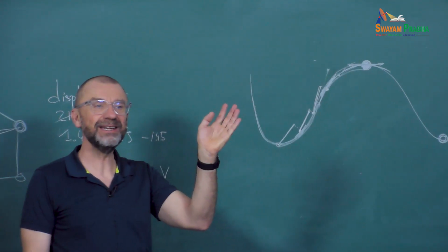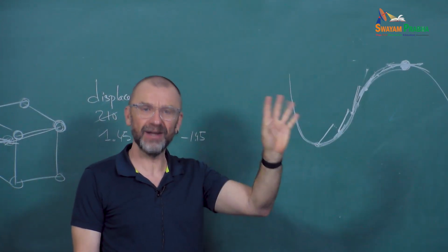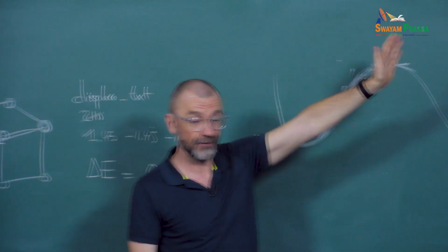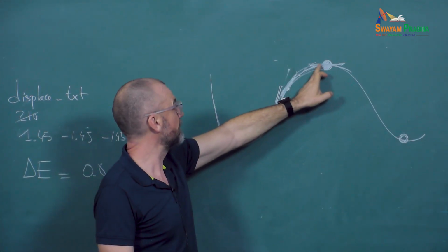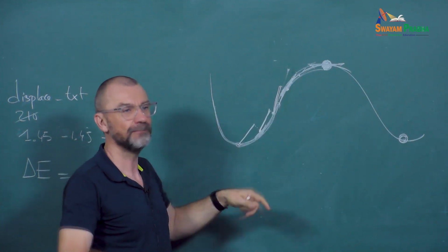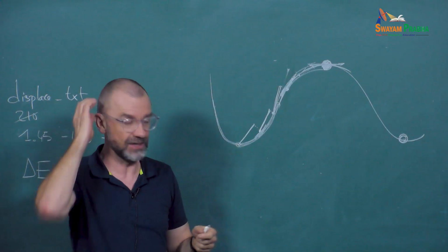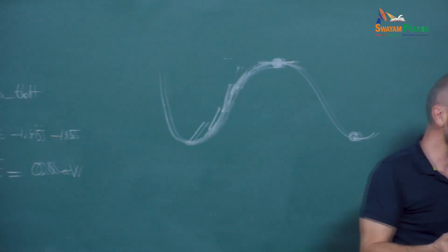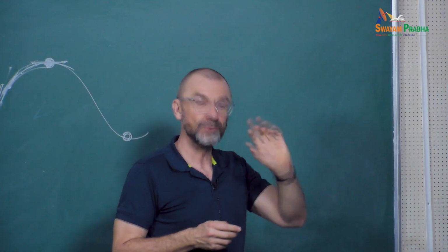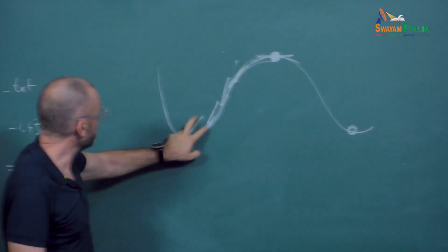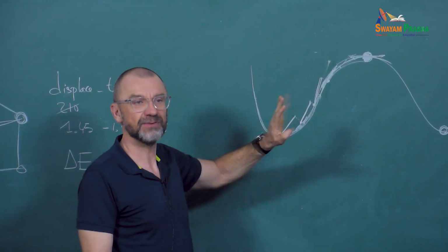Now, this is in 1 dimension. In 3n dimensions, reality is much, much more complicated. So sometimes you just never find an activated state. Sometimes when you do the minimization, you realize that you've gone over a valley without realizing it, and so you are no longer connected with the initial configuration. A lot of things can go wrong in these calculations. But if you spend the time needed for it to work... there are many numerical parameters involved in this method, like the size of these steps here, the number of energy minimizations there, etc.